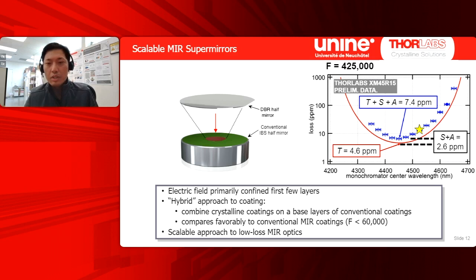So this has been a very successful approach. You see that we've characterized these hybrid mirrors, and at the center of the stop band, in this case about 4.45 micron, the finesse is well above 400,000, right? The total losses there are about 7 ppm, with a very favorable breakdown of transmission of about 5 ppm to about 2.5 ppm of parasitic losses.